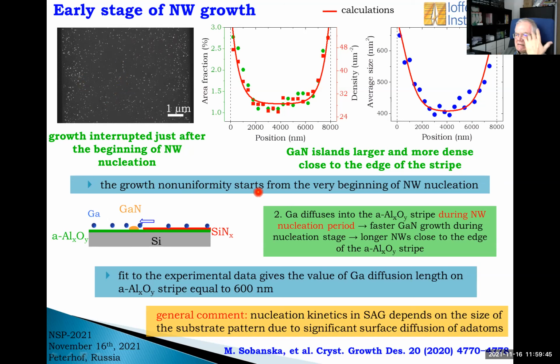And this led us to the conclusion that the diffusion scenario is something like that: at the beginning, gallium is delivered everywhere, but as soon as the first gallium nitride island appears here, then it starts sucking gallium from the mask. So these islands get more gallium than the islands in the middle.